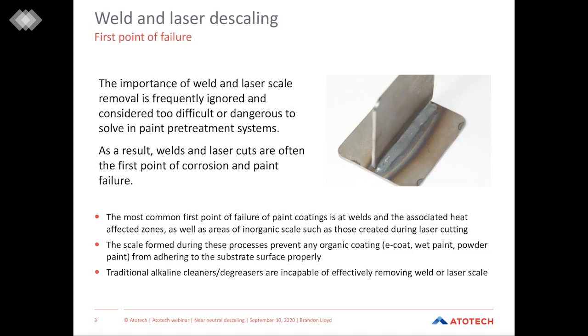So the most common first point of failure of paint coatings is at the welds and the associated heat affected zones, which we'll see a little bit later, as well as the areas of inorganic scale, such as those created during laser cutting or plasma cutting operations. The scale formed during these processes prevents any organic coating, being E-coat or KTL, wet paint, powder paint, or any combination of these, from adhering to the substrate surface properly. And traditional alkaline cleaners or degreasers are incapable of effectively removing this weld or laser scale.